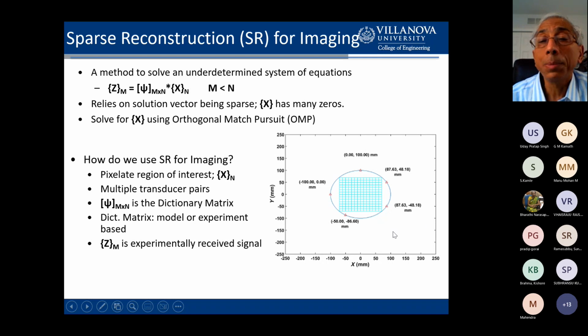Let's suppose I have a plate over here, and my defect, I believe, lies somewhere in this grid. One of the cells in this grid, or maybe more than one cell, is where my defects are. My strategy would be to put a few transducers. These little triangles you see here are the transducers. There are 5 of them in this particular case, distributed around a circle that surrounds the grid in which the defect is supposedly located. One thing I do know is that typically the number of defects tends to be very small. Hopefully that's the case, otherwise your structure is no good.